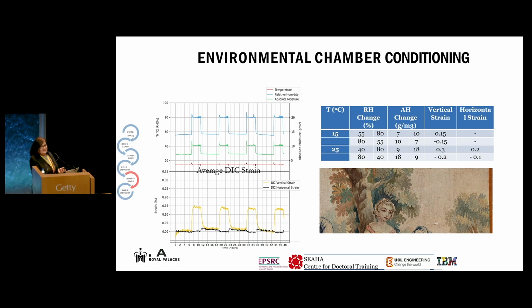Okay, now this has a lot of explanation. So the experiment involved 4 environmental cycles with RH changes between 40 and 80%, with a period of a fixed soak at each extreme and a stable temperature. We repeated the same set of experiments for 15 degrees centigrade and another one for 25 degrees centigrade. The top graph shows the RH, absolute RH and temperature graphs for the cycle at 15 degrees centigrade. However, for this temperature, the chamber could reach only 55% as the lowest point. So for 15 degrees centigrade, the RH was changing from 55 to 80%,